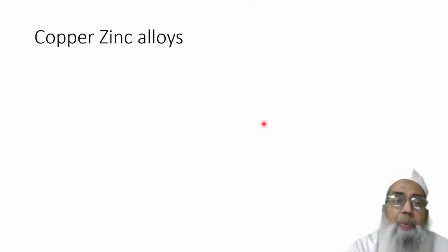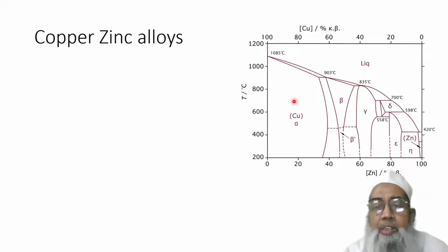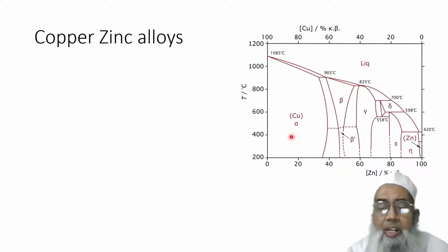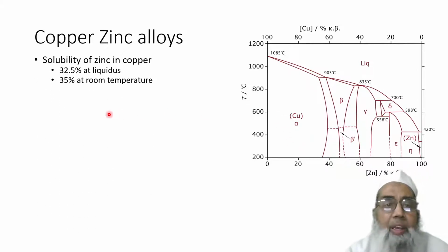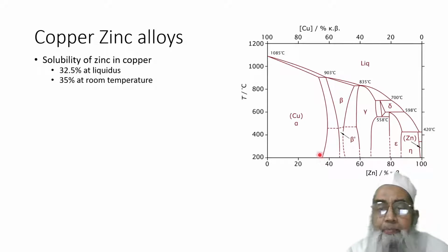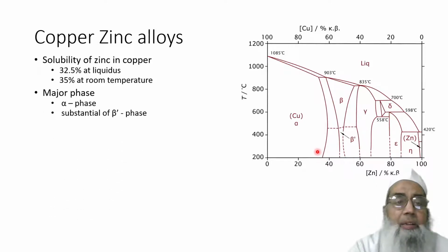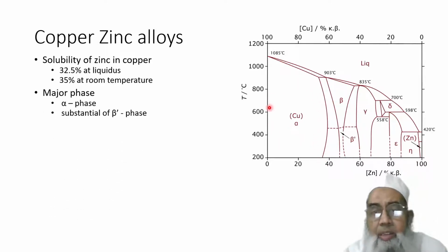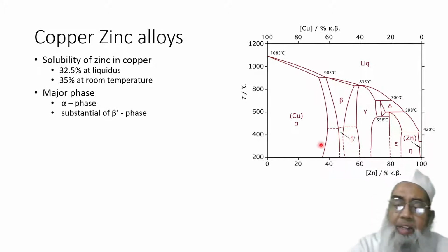Now, the copper-zinc alloy. If we look into this phase diagram, initially copper has a small solubility, with 32.5% at liquidus and 35% at room temperature. The major phase is the alpha phase, while having a substantial beta dash phase.